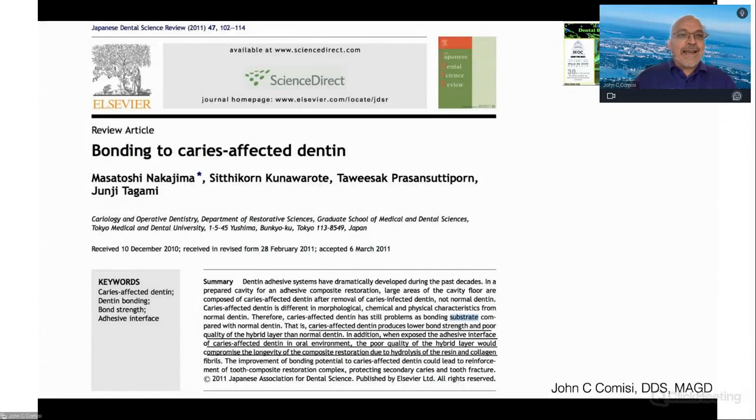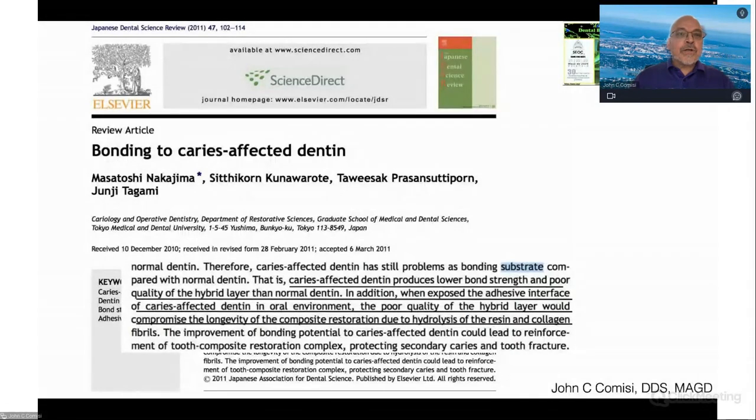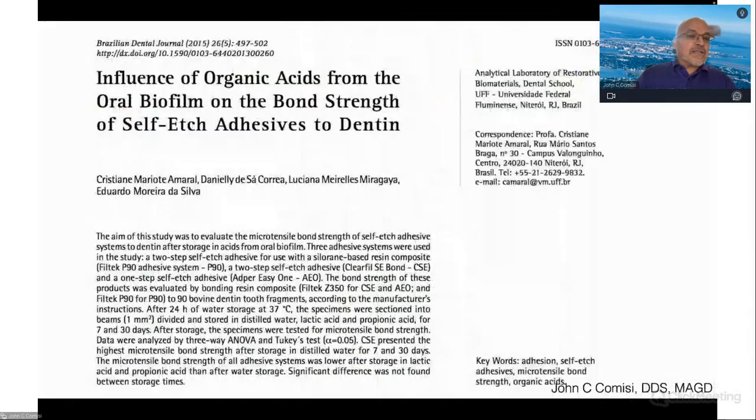When the manufacturers tell us the overall shear bond strength in megapascals for all of our bonding agents, it is all done on caries-free surfaces. But in reality, when we are bonding to caries-affected dentin, we have a very, very low opportunity for really good bonding processes to occur because of the hydrolysis that we talked about, and the overall enzymatic breakdown that is occurring on a regular basis.